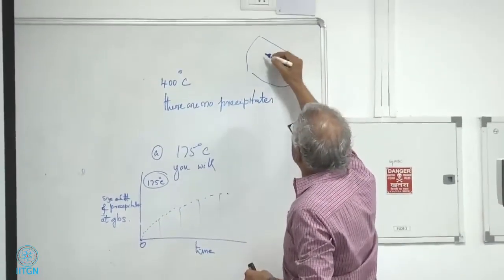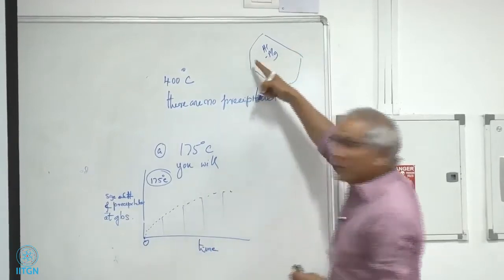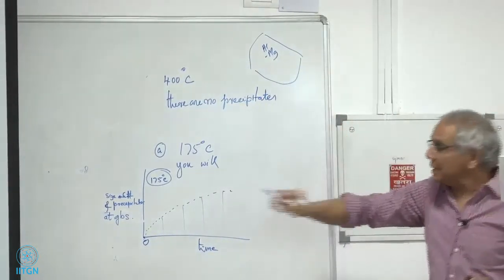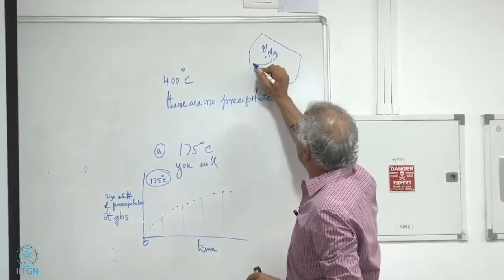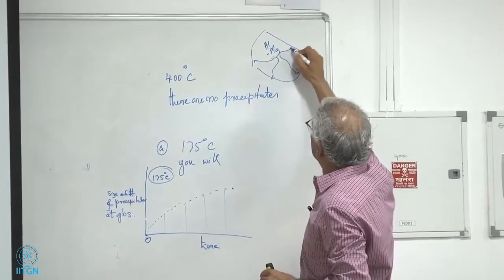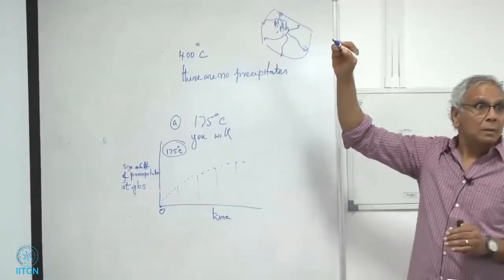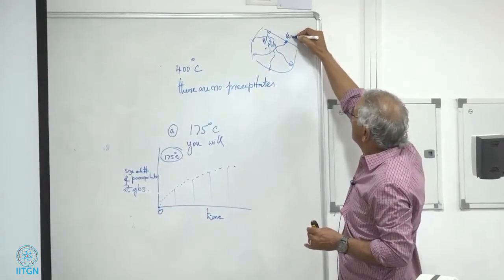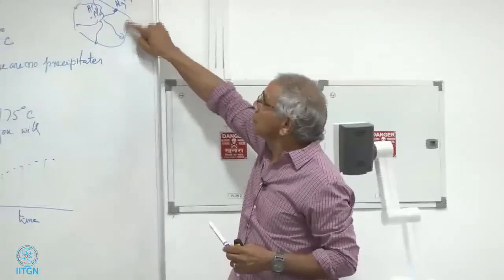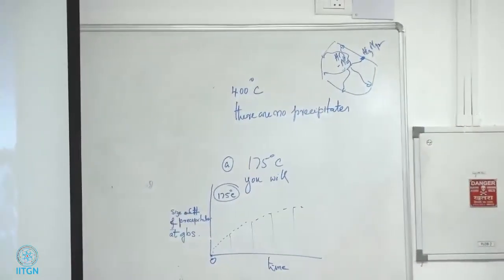Either they may grow or the number can increase, right? So the magnesium, there's my grain. These are my grain boundaries. My grain has aluminum magnesium. But at this temperature, my magnesium is diffusing to the grain boundaries and forming Al3Mg2. So the magnesium is coming out of the solution. It's diffusing much faster than aluminum, and it's forming Al3Mg2 precipitates.